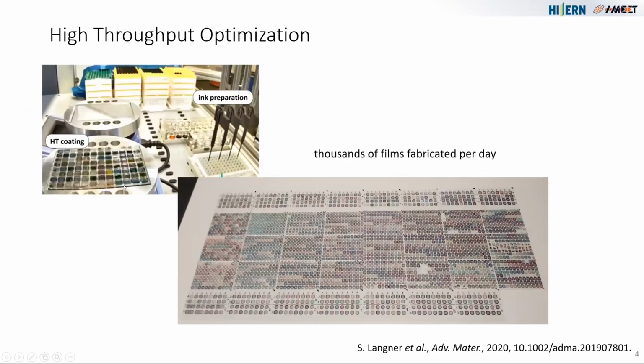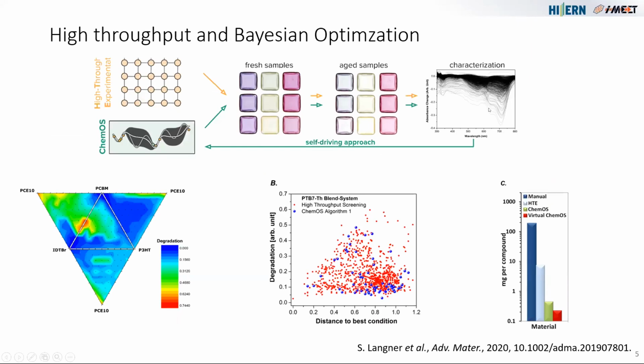The first part, where we did OPV layers by drop casting. This is what really started us to go into this high throughput robot-based stability approach, where with the pipetting robot, we could make thousands of films, and we could then change the composition on all of these and degrade them under light. And then after all these films were degraded, we measured the absorption spectrum again. So we have thousands of absorption spectra, fresh and aged. We subtracted the absorption spectra from fresh to aged, so we see the loss. We also can sort of see in which region the losses are the highest. But in the first approach, we were just integrating the total absorption loss.